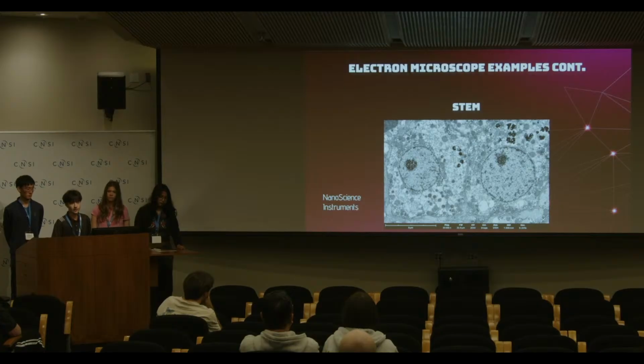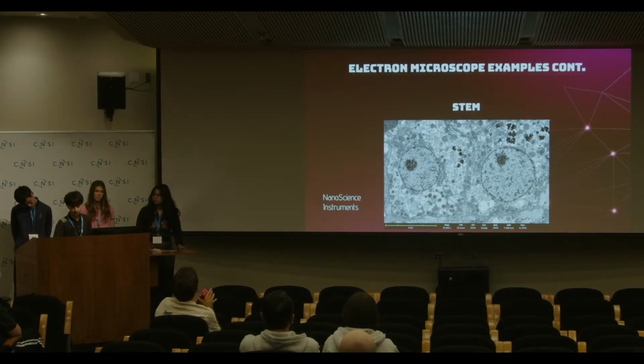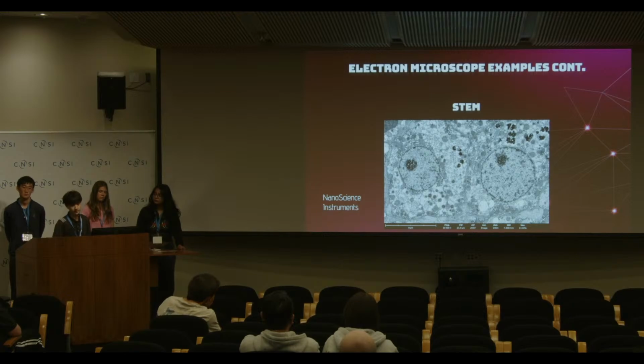These include bright field and dark field imaging, as well as X-ray spectroscopy, which can show the chemical elements present in different parts of the sample. One of the biggest advantages of STEM is that it keeps the extremely high resolution of TEM, often better than 50 picometers, but adds the ability to gather elemental and structural information at the same time. Because of these features, STEM is especially useful in materials science and nanotechnology, where scientists need to study not just what something looks like, but also what it's made of and how its atoms are arranged, all in one experiment.